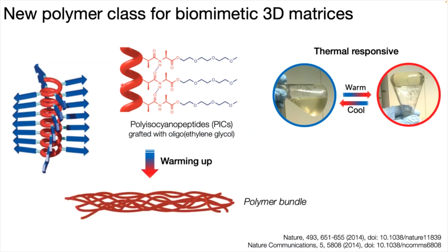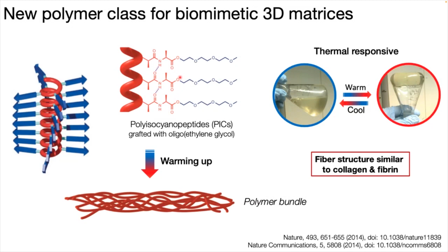The process behind this gel formation is really a formation of polymer bundles. The ethylene glycol side chains, once you start warming up, become hydrophobic, and they are attracted to each other, and they form these bundles. And this type of fiber structure is very similar to what is observed in collagen and fibrin.